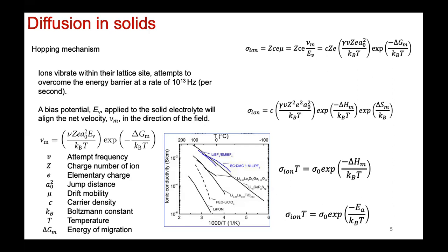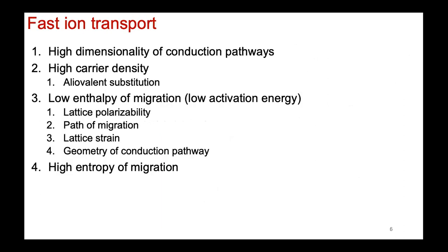But really all it comes down to is if you know the crystal structure, you can calculate the ion conductivity at each temperature. What you want to do is increase ion conductivity at room temperature, because that's where most of us live. Although if you have a high temperature application, then you can think about materials that are more stable at high temperature or low temperature application. But for the most part, if you're thinking about electrifying vehicles, you're thinking about room temperature applications. Even if you're in a very hot or cold environment, you deviate mostly from room temperature.